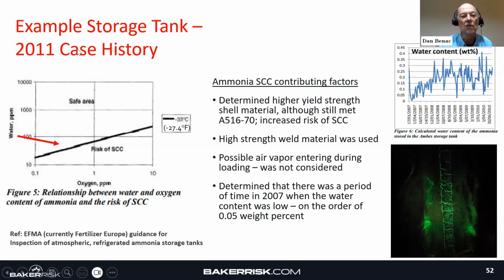If you see this curve over here on the left, you can see if your oxygen level is too high and your water level is not high enough, you can potentially have a risk of stress corrosion cracking. So what do you do? Well, you make sure you have enough water and you make sure you don't have oxygen in your system. But in this particular case, you can see some cracking that occurred.